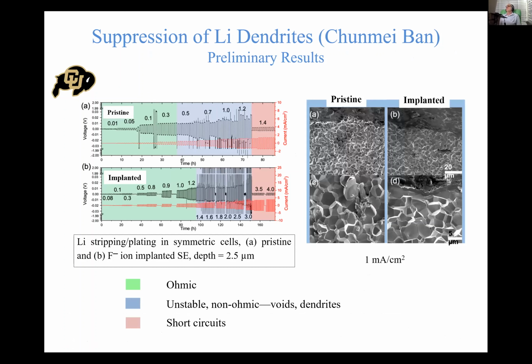So these are preliminary experiments done in Chunmei Ban's lab. And what she did is she took a pellet of LLZO or maybe LLZTO, and she implanted part of it with fluoride ions and left part of it pristine. And then made symmetric cells where she runs the lithium either through the pristine parts or through the implanted parts. And so what she sees is that in the pristine system, these are, by the way, on two different timescales. In the pristine system, she can get ohmic behavior up to about 0.3 milliamps per square centimeter, after which it goes unstable, and then above 1.2 milliamps per square centimeter, she gets a short circuit. In the implanted region, she gets ohmic behavior up to 4 times higher, up to 1.2 milliamps per square centimeter before it goes unstable, and then you don't get a short circuit until 3.5 milliamps per square centimeter, 2 to 3 times higher than the pristine.